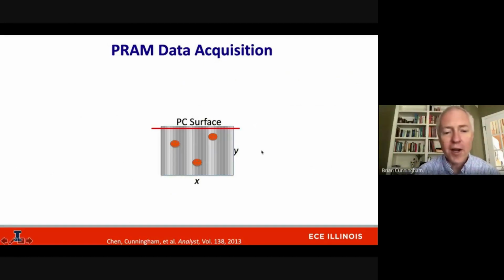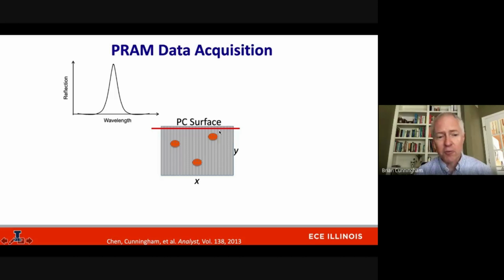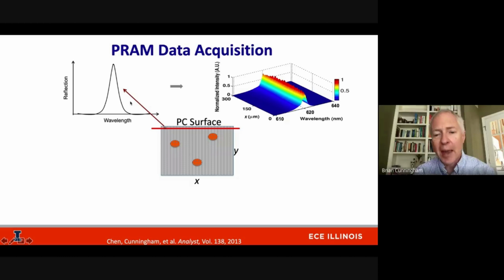So to acquire a PRAM image, we take the light from the LED and it's focused into a line that spans across the photonic crystal. Each point along this line is represented by a resonance reflection spectrum from the photonic crystal. And in one capture from our spectrometer, we gather 512 spectra, each from a different point along this red line.